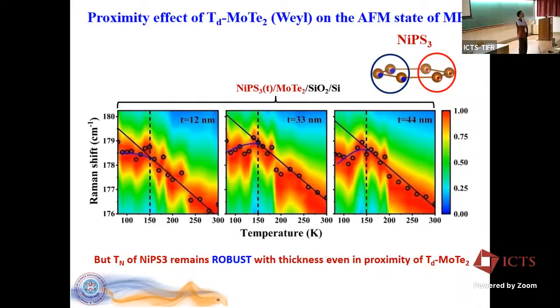NiPS3, now that was the game changer. This guy is extremely robust. Okay, so this is all with MoTe2. Now we are showing different thicknesses that we could do. I mean, the thicker sample has no response. Even the intermediate ones, 44, 33, 12 nanometer, they are still robust in terms of the Néel ordering. Okay. The question is, if MnPS3 and FePS3 showed lowering of the Néel temperature, why not NiPS3?